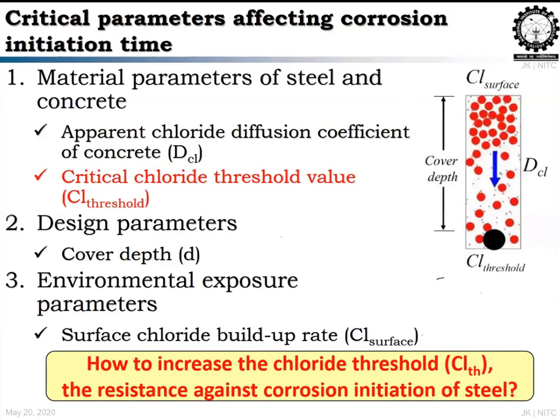You should make a very good quality concrete. Even then, if the chloride reaches the surface of the steel, the steel should have a capacity to withstand the corrosion. So even if the concrete is very bad, based on the quality of steel and its resistance against corrosion initiation, your corrosion initiation time will be delayed, and thus your service life will be extended. We will be looking mostly at the concrete and steel and the factors influencing the changes that will happen in the concrete which lead to corrosion initiation.